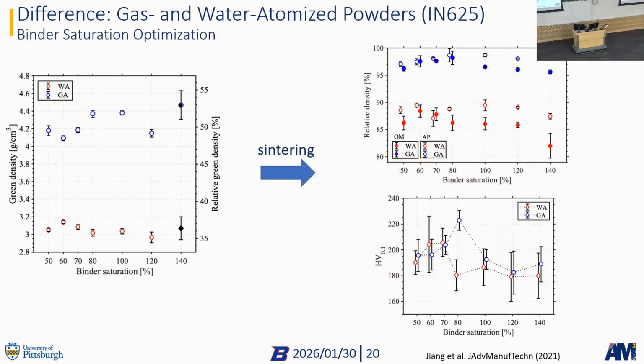So here we looked at the green density, so as-printed density, and then also density after sintering. And what we could see right away is that the green density really translates into the sintered density. So the higher your green density, the higher your sintered density. And then, as we saw before, sintered density also results in the mechanical properties. So whenever our green density was highest, sintered density was highest, and mechanical properties were the highest, right? So what you can learn from this is the better you print your material, the better your final mechanical behavior, right?